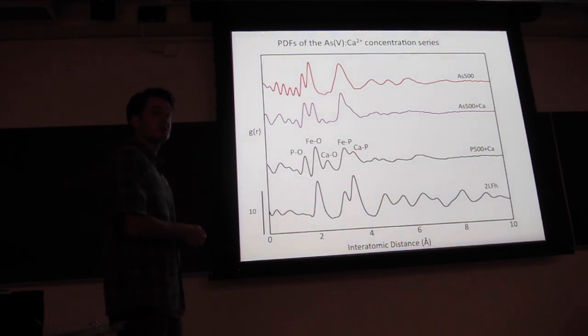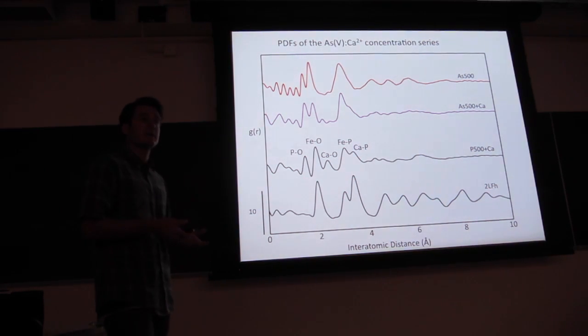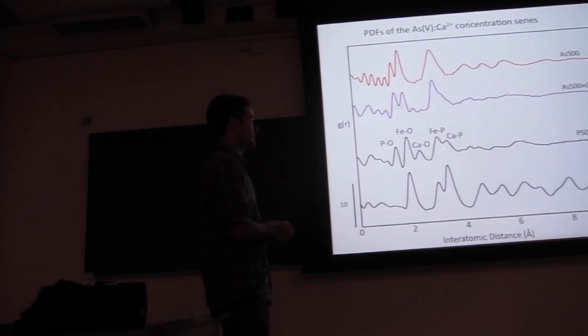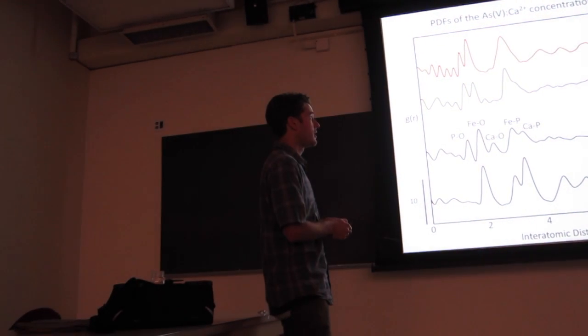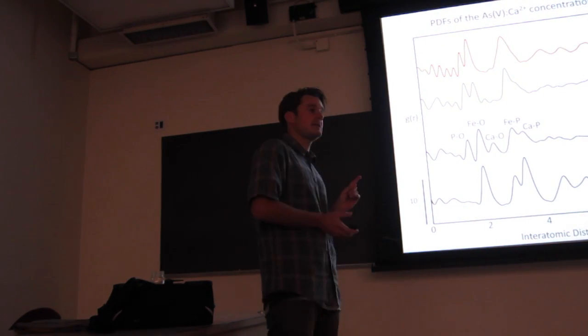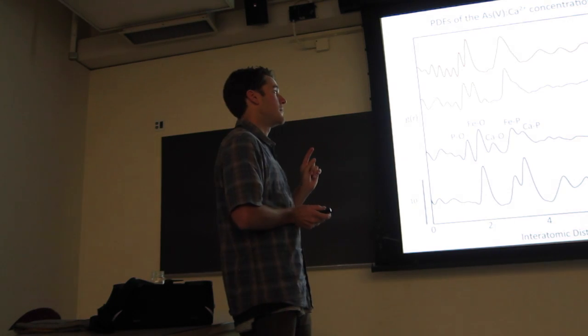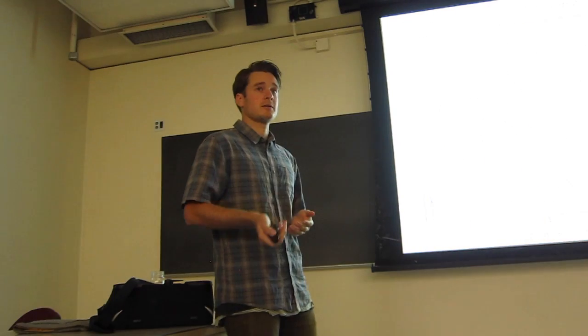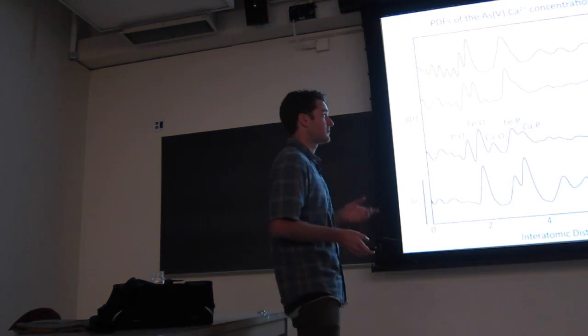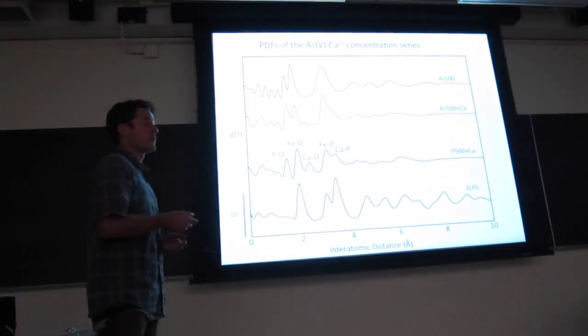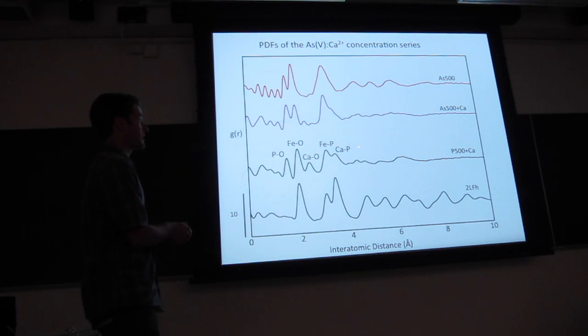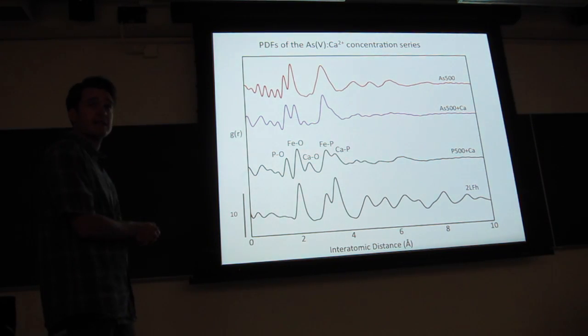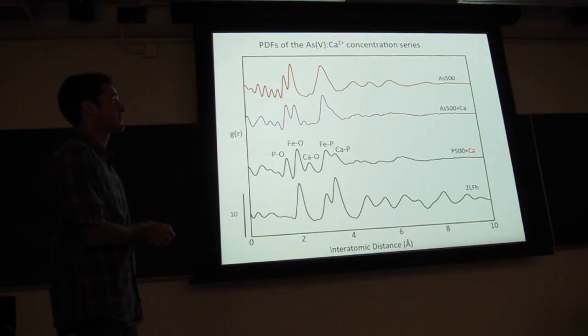So strongly sorbing calcium would show up more than electrostatic calcium in using the PDF. And so this peak right here, this shoulder, the position of that peak is exactly where it is in calcium phosphate minerals like hydroxyapatite. And so we expect this shoulder here to be due to calcium and phosphorus. But we argue against the formation of a distinct calcium phosphate mineral, because if this were due to a distinct calcium phosphate mineral, we would see peaks from it going further out. But we don't. We see that after about 7 angstroms, there's nothing.